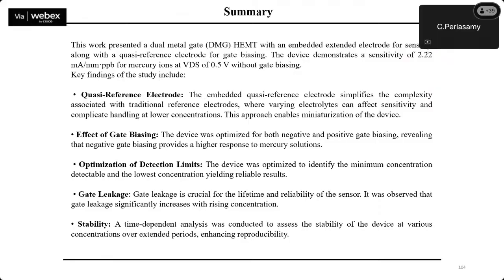However, we have developed and demonstrated the HEMT structure for pH and heavy metal ion detection, but still there is scope to study the stability, because we have observed gate leakage in the fabricated structure, and subsequently we tested for reliability. We have observed that the output characteristics of the fabricated structure degraded. So there is still scope for us to study further to improve the performance of these proposed devices. It is under process.